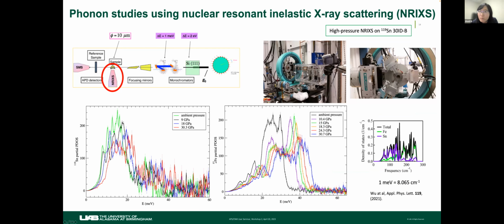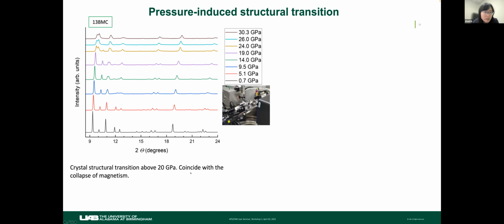And also, if we include our iron data and compare the tin and the iron specific phonon density of states, we notice this phonon mode above 30 milli-electron volts on the tin corresponds to, we concluded, the vibration mode coupled with iron. So that means this mode is coming from the iron-tin Kagome layer. We also compare with the previous calculations done by this paper on the specific phonon density of states on tin and iron, and the agreement is excellent. If you do a simple conversion of the frequency into milli-electron volts and the cutoff frequency, all the major modes are there.